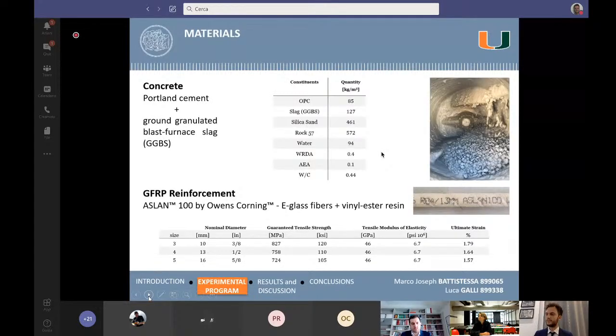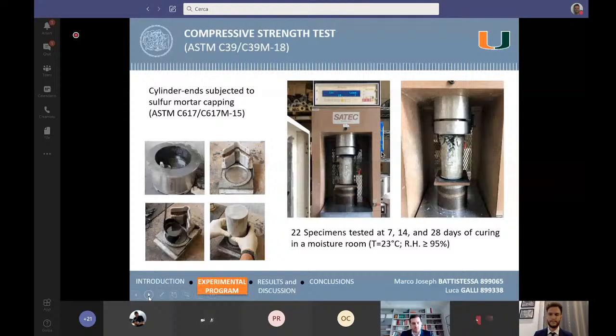During our experimental program, we chose the materials according to a previous thesis work where the new test was introduced, in order to make comparisons with it. All the specimens were made out of the same kind of concrete, whose binder is composed of Portland cement and slag, and the same kind of commercially available reinforcement, which is covered by a sand coating and a helical wrap of the surface. In this way, we also want to limit as much as possible the variables to be studied. First, we performed several compressive strength tests in order to have a mechanical characterization of the concrete. We carried out tests after 7, 14, and 28 days of curing in a moisture room at 23 degrees and a relative humidity of 95%.